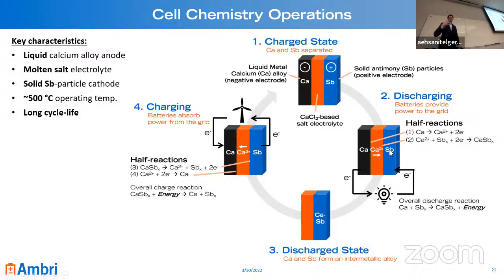Yeah, so the electrode itself is actually not, this is a simplified image, of course. It's actually solid particles distributed in that region with salt in between. And so you end up getting deposition of the calcium throughout that electrode. You do see a bit more preferential deposition and conversion closer to the front interface and then progressing back in, but it does all get accessed.